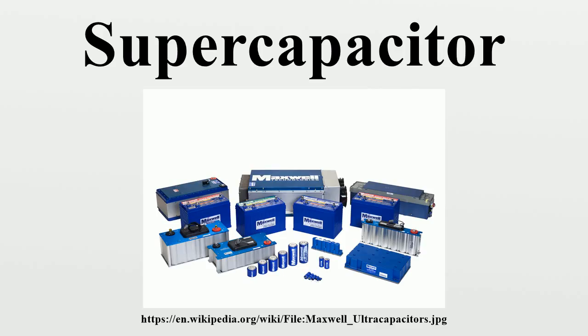Applying a voltage to an electrochemical capacitor causes both electrodes in the capacitor to generate electrical double layers. These double layers consist of two layers of charges. One electronic layer is in the surface lattice structure of the electrode, and the other, with opposite polarity, emerges from dissolved and solvated ions in the electrolyte. The two layers are separated by a monolayer of solvent molecules, e.g., for water as solvent, by water molecules, called inner Helmholtz plane.